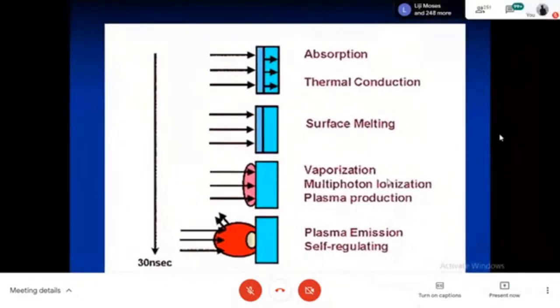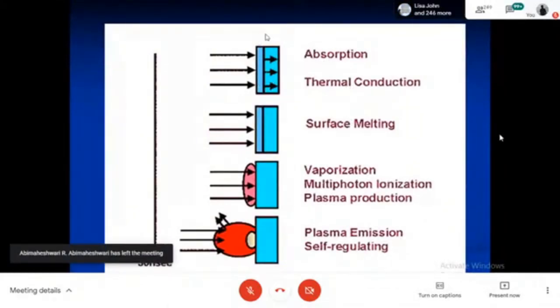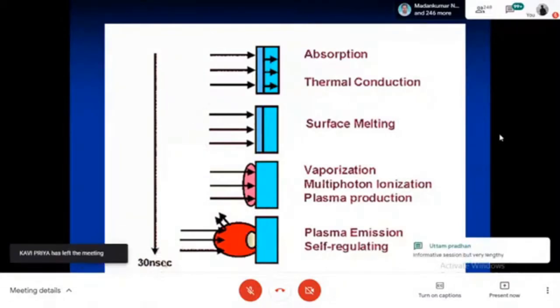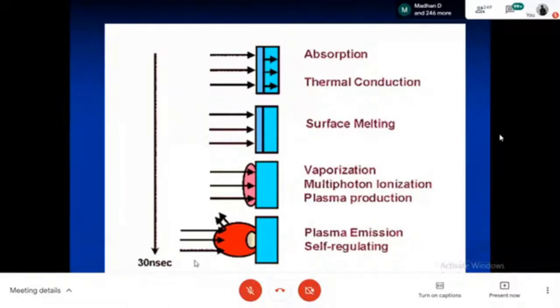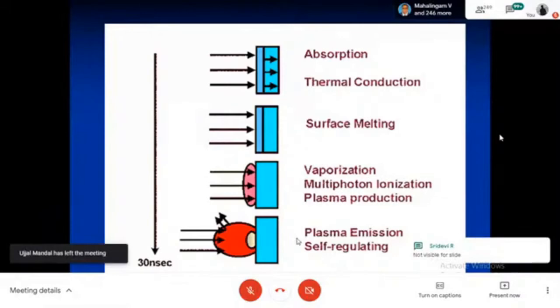And so the mechanism is the moment laser hits on this target, then there is a very small thickness of the surface melting, and this surface melting induces the vaporization followed by multiphoton ionization, which produces the plasma. Then the plasma carries the ions towards the substrate. So the entire process is done very quickly, within 1 to 30 nanoseconds. So you can just see the speed with which the process happens.